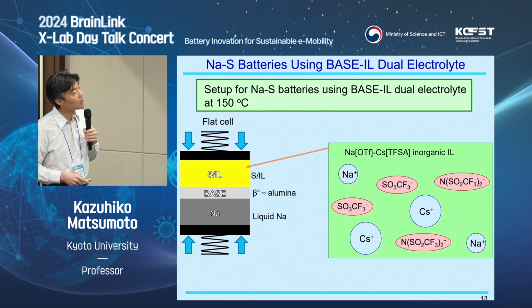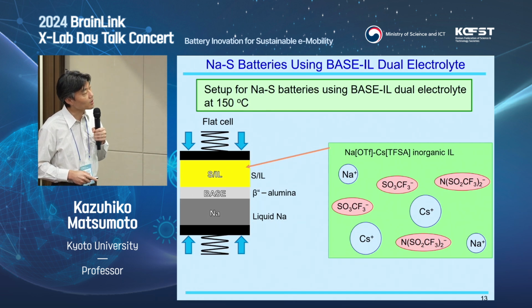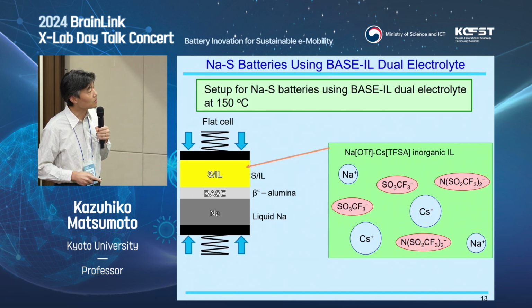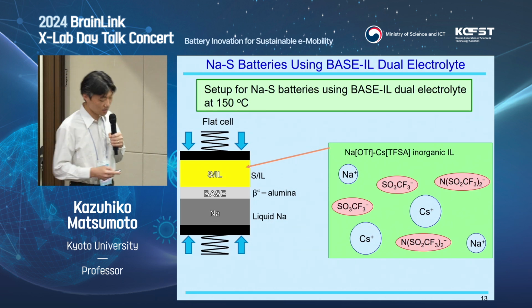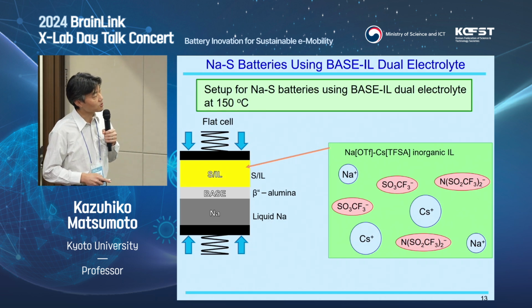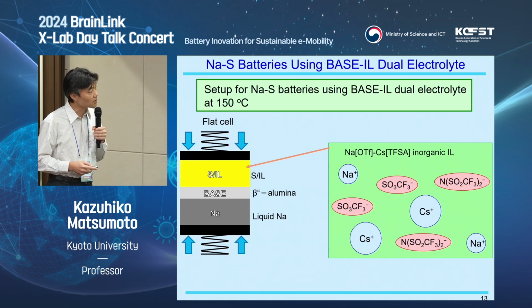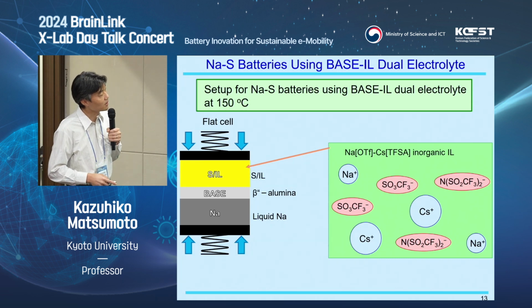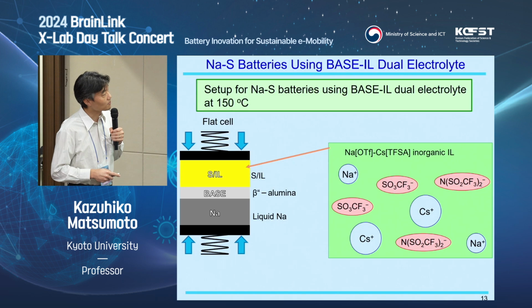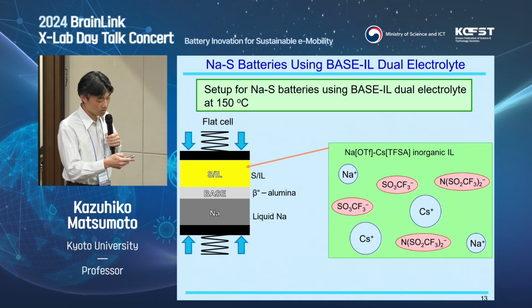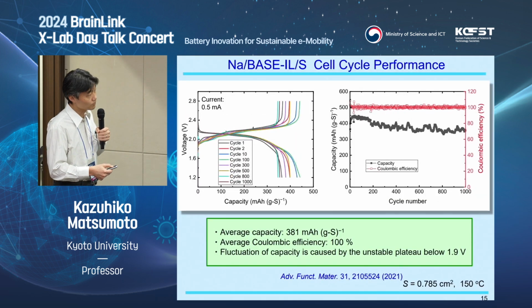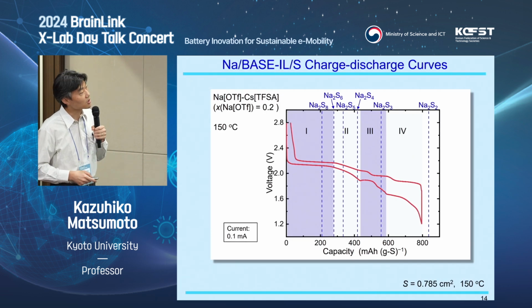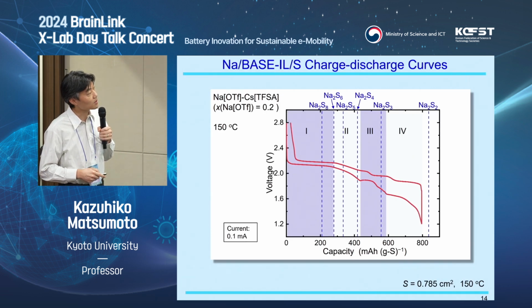And after a long-term screening, we reached this inorganic ionic liquid with the sodium triflate and cesium TFSA. And this triflate ion is actually necessary to dissolve polysulfide. But anyway, we made that a flat type cell and then discharge. And this is the discharge charge curves with the different polysulfide species. And again, we use that inorganic ionic liquid and beta alumina for this purpose.